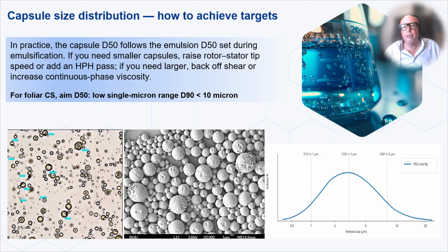Preventing droplet inflation by carbon dioxide release is crucial. This happens with NCO excess or too fast reaction at high temperatures. For foliar CS, we target D50 in the low single micron range and D90 under 10 microns.